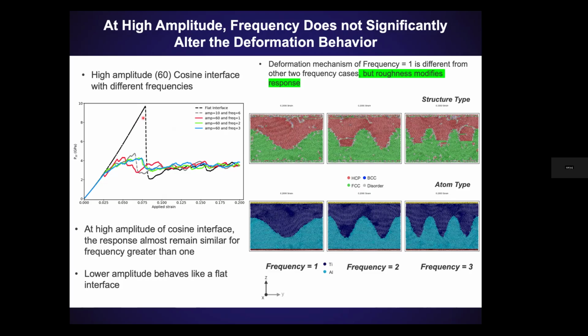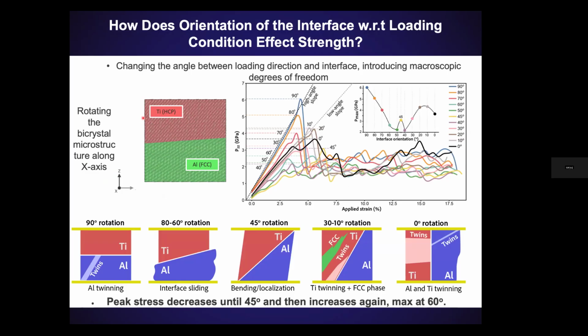So far, what we've seen is that a rough interface is going to have a lower yield strength. A higher amplitude interface is going to be a little weaker than a lower amplitude interface. And then the frequency at those high amplitudes doesn't matter. So if you process it in a way where you have one perturbation or 3 or 5, it shouldn't matter that much in terms of its stress-strain response. But what will change right away is if you have any perturbations at all in your interface, and most interfaces atomically are never flat. The other thing is when you're looking at components, you don't just have bimetals nicely lined up with your loading direction.